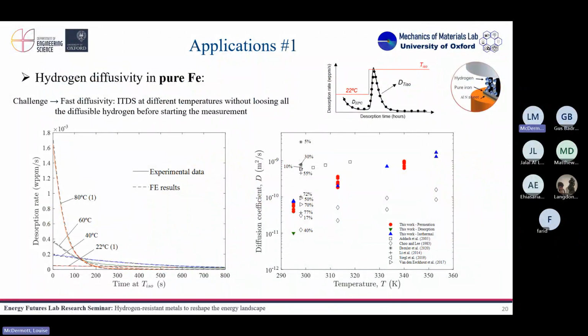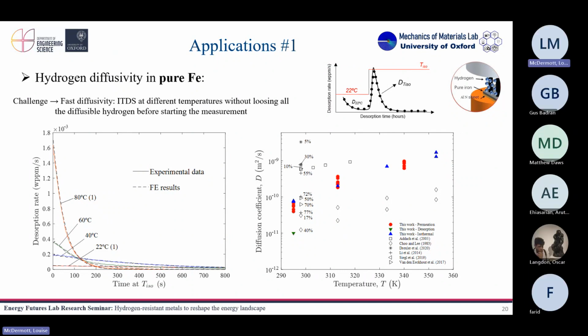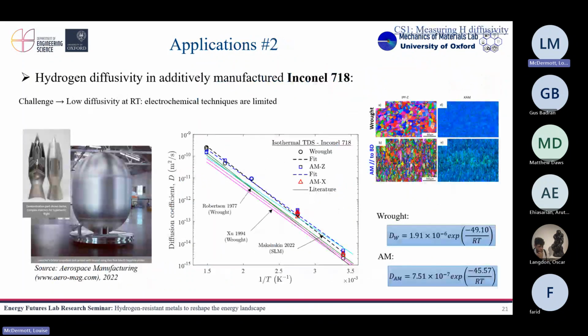Then, as applications of this isothermal TDS technique, we managed to apply it to pure iron at different temperatures, which is usually very hard because hydrogen diffuses really, really fast in pure iron. You charge it, and in less than 1 hour, probably you don't have any hydrogen left in pure iron. So we were able to measure diffusivity there at different temperatures. And Claudia is familiar with this: we applied this isothermal desorption also at very high temperatures, even 400 degrees, because it's another advantage of TDS, that you can heat your sample as high as you want.